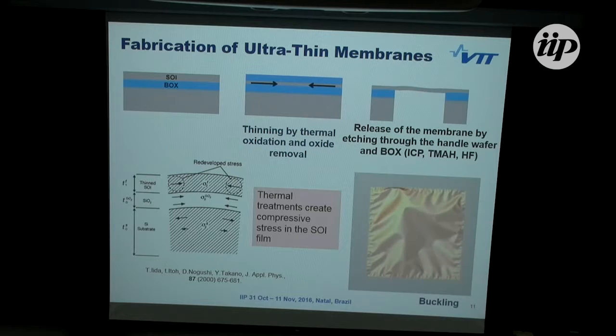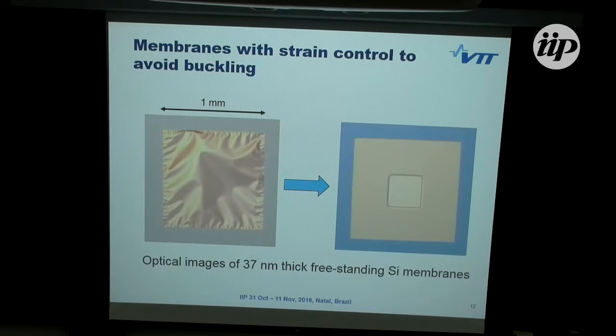And when the membrane is released, meaning etching from behind through the handle wafer and removal of the buried oxide, then this is the outcome. It's a buckling film. This is a 37 nanometer thick, 1 square millimeter film, but the compressive stress is released and it becomes buckled. So we wanted to avoid this, and then we came up with a process which we can use to make these kind of flat membranes.